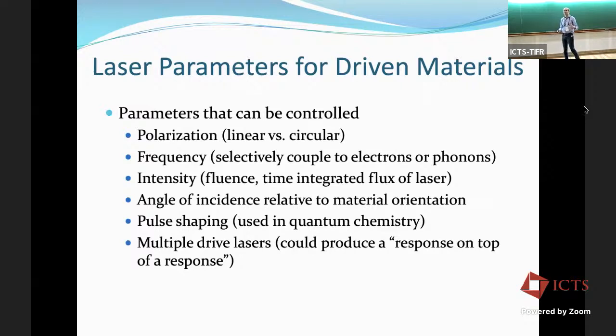So for a fixed frequency of light, as you sweep the intensity of the light, you can get very different responses. So when I talk about the nonlinear phononics, if the intensity of the light is not sufficiently large, then you won't push the phonons into an anharmonic regime. You'll remain in that harmonic regime. But beyond some critical intensity of the light, then you start to see anharmonic effects. And so the response of the material can vary dramatically depending on how intense the light is that you're shining.